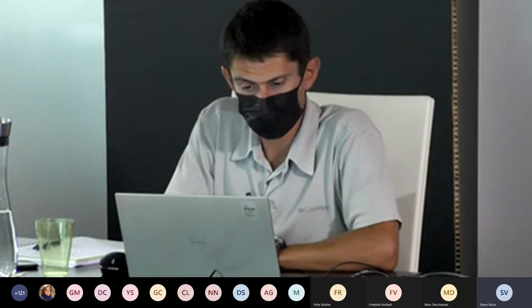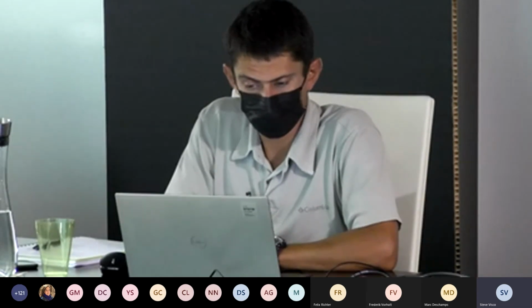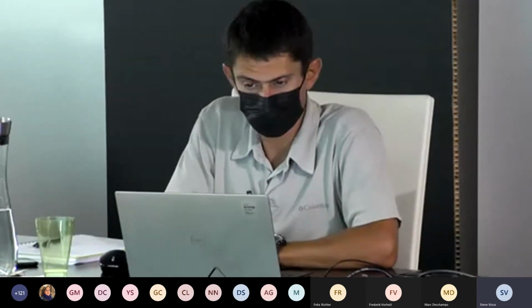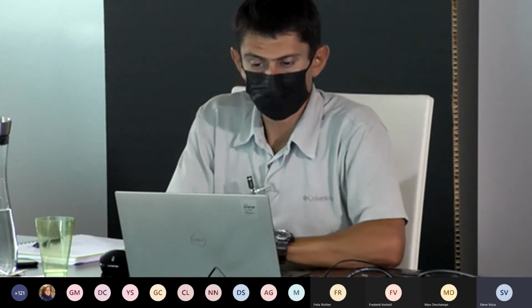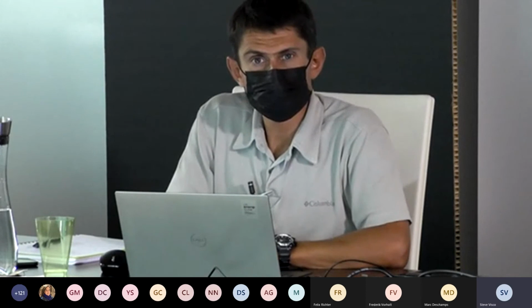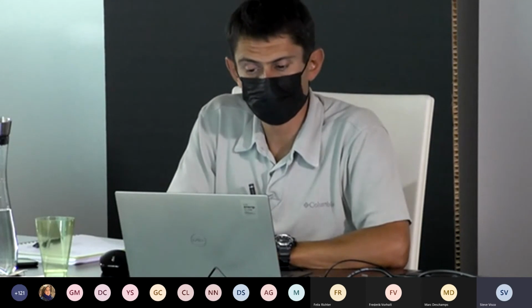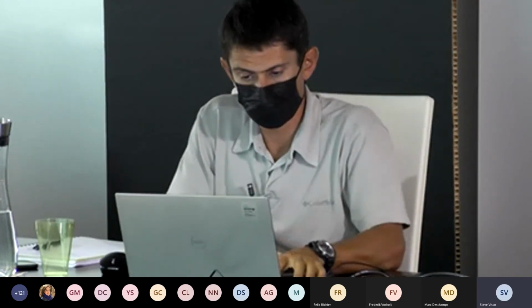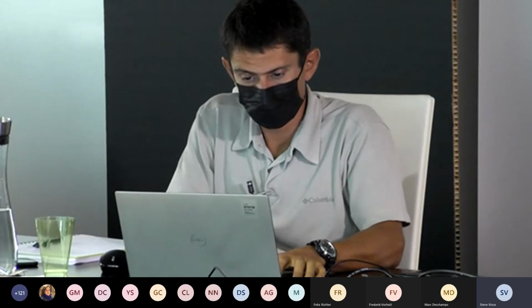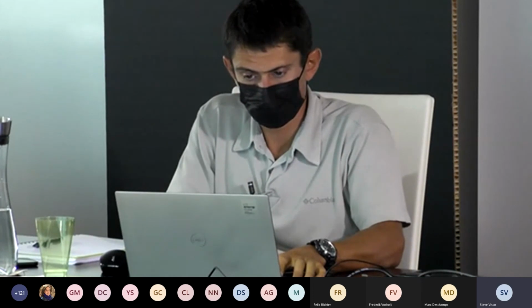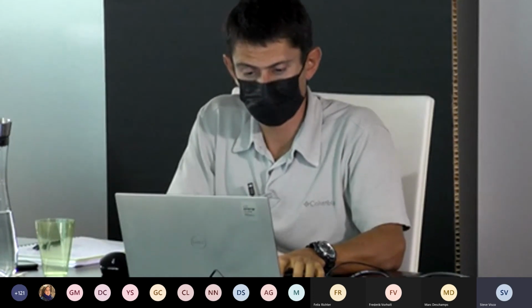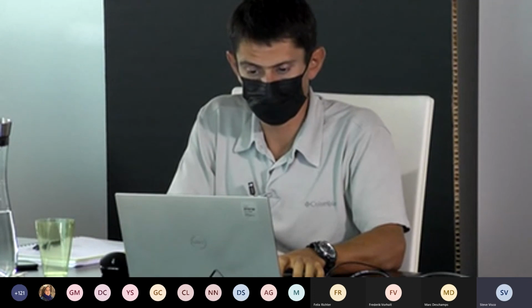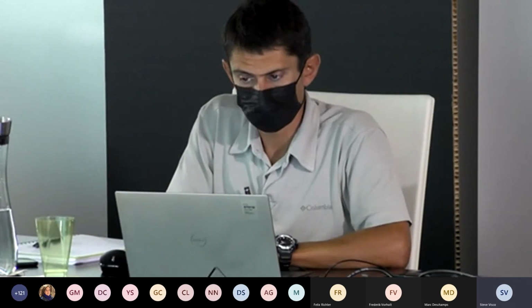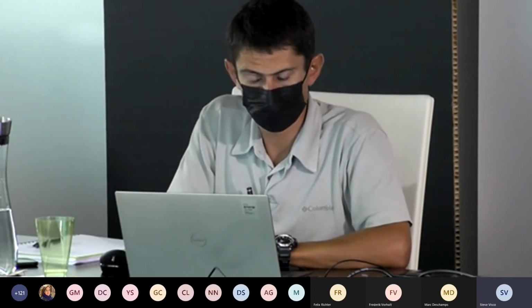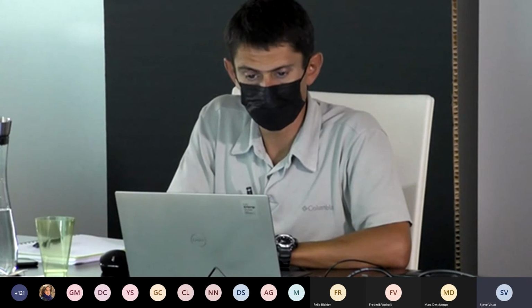However, when we go to extended cycling and we have multi-layer stacks, it's possible that there will be an effect of pressure, that it may assist long-term cycling. But for the time being, all of our testing is done with very effectively light spring pressure. So we don't compress the cell. It's very different than, say, the Toyota approach, where they have composite cathodes that really require tremendous compression to keep the solid-solid interfaces in touch. So we don't do that.